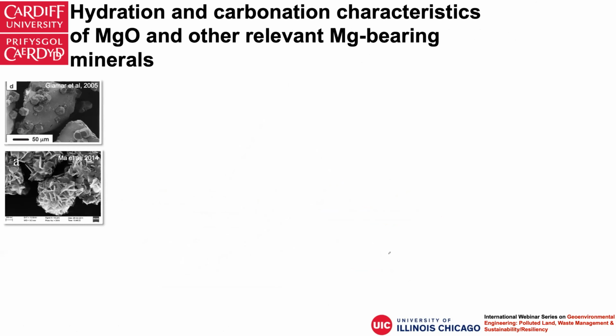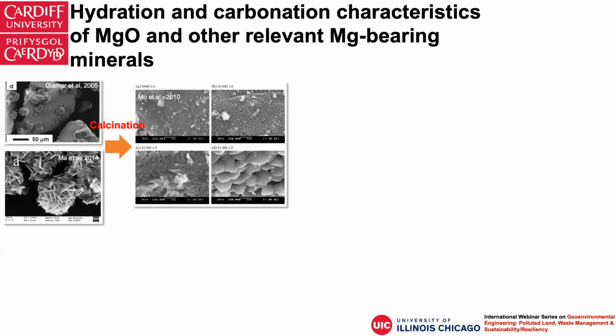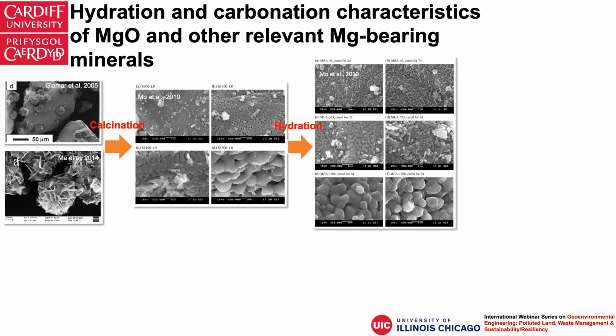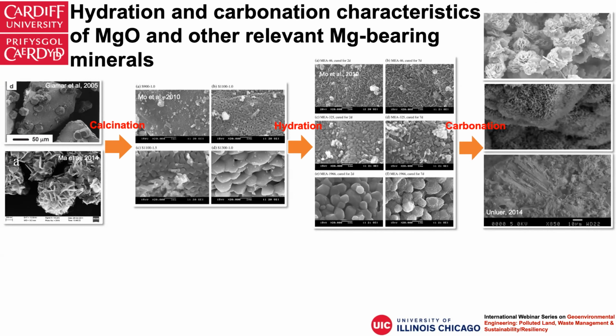And these figures show the whole picture of the magnesia-bearing cements. The first two figures show you the microstructures of magnesite and brucite, either from the magnesite or from the precipitation of seawater. And then you can use different calcination temperatures in order to get magnesia samples with different reactivities and different surface areas. Then you put the magnesia in water to hydrate it, and you get different morphologies of brucite and different particle sizes as well. And then if you carbonate these magnesia or brucite, you get different morphologies of different hydrated magnesium carbonate phases.